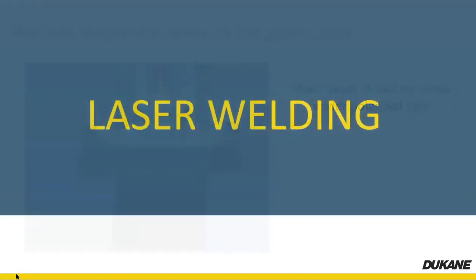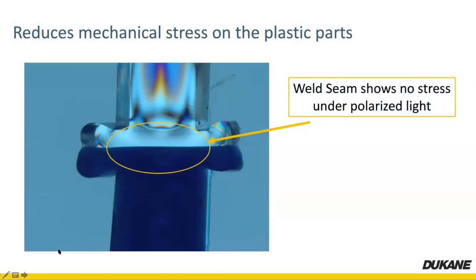So this screen is showing a microtome of a hot gas weld. You can see the lack of color at the weld seam, which means there's no stress. We've annealed this part as we've been welding it.